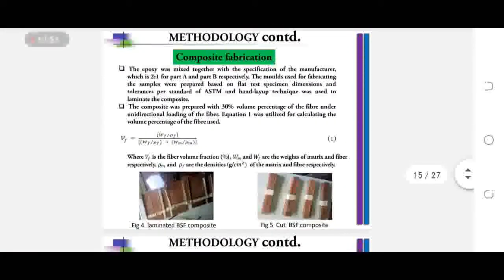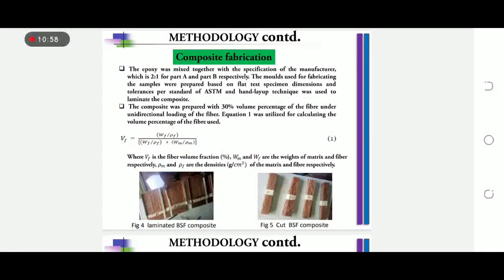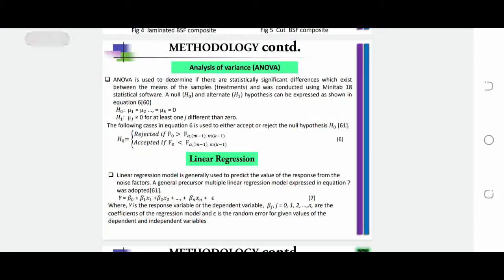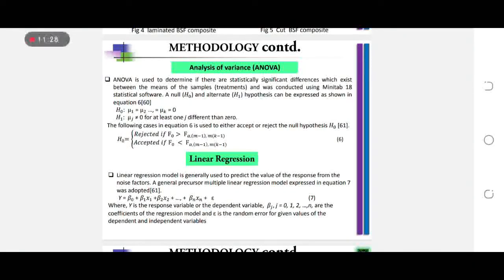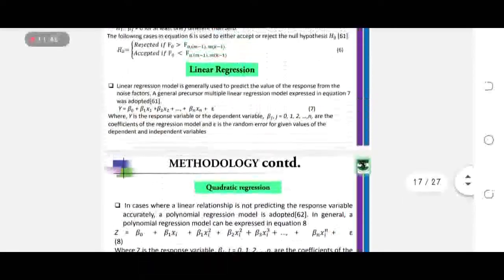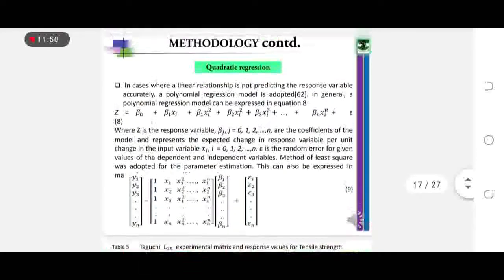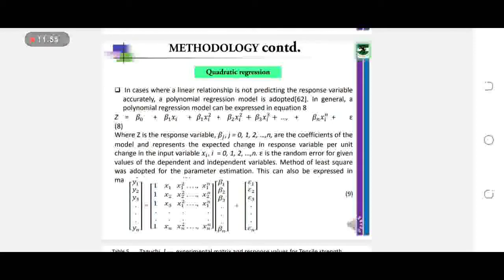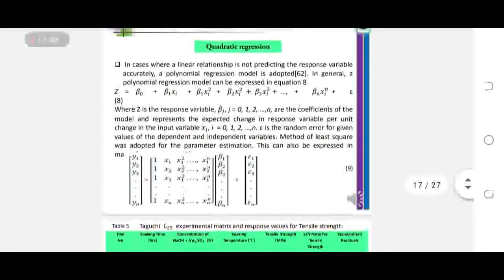For composite fabrication, we fabricated our composite based on ASTM standard, and the hand layup technique was used to laminate the composite. Equation 1 shows the formula we used to calculate our volume fraction. We used analysis of variance to analyze our data, and a linear regression model was generated based on equation 7. Then ANOVA, which was done, uses equation 6. If the observed value is greater than the critical value, we reject the null hypothesis, but if it's less, we accept the null hypothesis. It was done at the 95% significance level. A quadratic regression model was also generated. The quadratic equation in equation 8 was adopted, and equation 9 is the matrix form of equation 8.